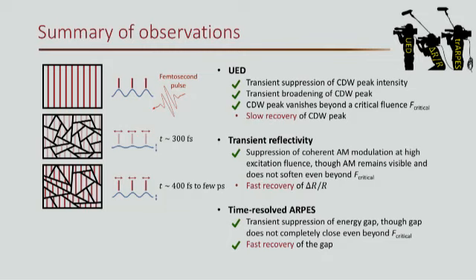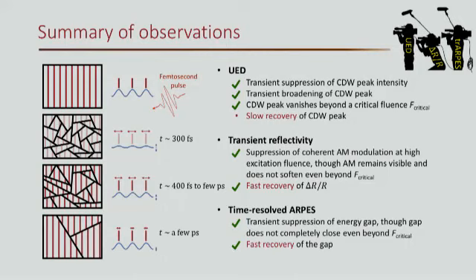because what you measure in terms of the timescale of delta R over R, besides the electron-phonon coupling due to the relaxation of quasiparticles, is basically the relaxation of quasiparticles across the gap. And if the gap recovers, it's natural to expect that the delta R over R signals also recover pretty fast. Then what happens slowly is the destruction of the domain walls and also the recovery of the phase mode. And that explains why there's a slow recovery of the CDW peak intensity.